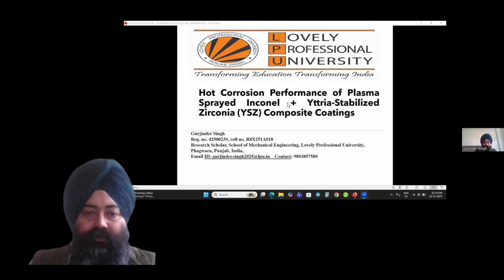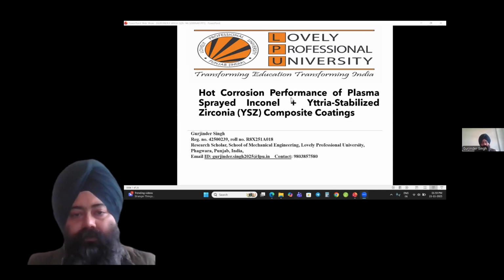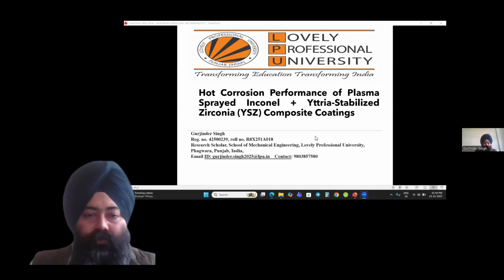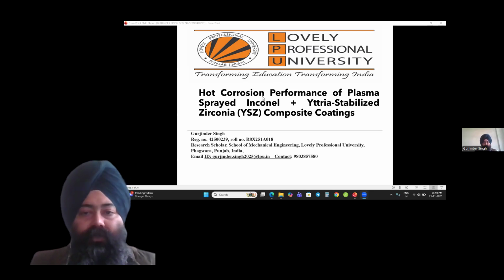My research mainly focuses on developing high performance coating for extreme environment conditions. And my topic is hot corrosion performance of plasma sprayed Inconel, which is basically a nickel-based superalloy, plus yttria stabilized zirconia composite coatings.